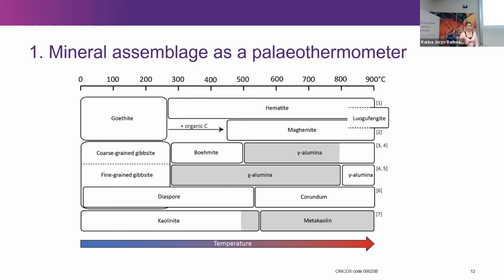And that's a mineral that no one had ever heard of. I needed a lot of help to figure out what that was in my XRD. And it's actually a high temperature iron oxide polymorph. And it's only ever been identified in one natural sample ever on Earth, and that's a Pleistocene basaltic scoria. These are experimental samples, not natural. This is quite interesting because if we were to find this in natural samples, then that might tell us that we've had fires of temperatures up around 900 degrees, which is higher than what we've ever measured currently.